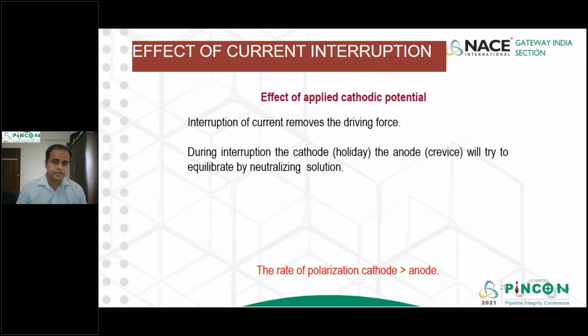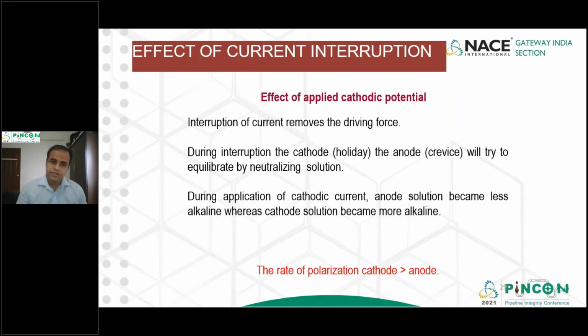cathodic protection. Now, during interruption, the holiday, the anode, will try to equilibrate by neutralizing the solution between the device and the holiday. So what happens in this phenomenon is the outside environment in the holiday is already polarized. The inside one is not that polarized, but because of the power interruption, the inside and outside try to neutralize. During application of the cathodic protection, again after the interference, anode solution becomes less alkaline because the equilibrium was established and suddenly the current was restored, and cathode solution becomes more alkaline. So this proves that the rate of polarization at the cathode is comparatively more compared to the anode. Anode is the crevice area.